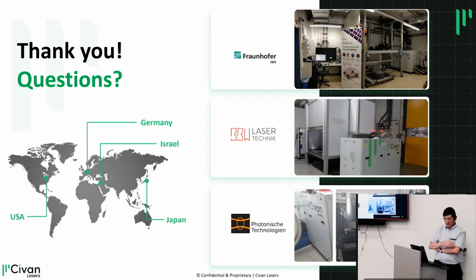Yeah, exactly. So our customers are going through certification processes for all the welds, but most of the time we don't have access to that data, and even when we do, we're not allowed to publish it. We ourselves started going through a qualification process. So we do X-ray, CT, and then we measure the Charpy test and the strength test and the strain and the hardness test and everything accordingly. There's a standard basically that you can certify a weld according to, and we're going through this to show that the welds are certified.